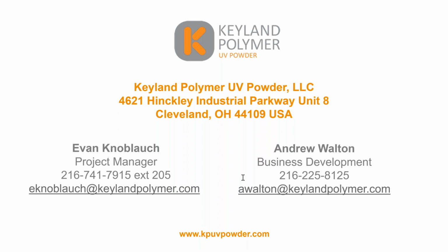Can you use high intensity infrared for the melt flow gel, then UV for the cure? Yes. The melt stage can be done with convection, whether it's shortwave IR or longwave IR, electric or gas. The powder doesn't really care. Ideally, what we want to do is melt it as quickly as possible so that it is prepared for cure. So the powder will perform well under any type of heat used for melt.